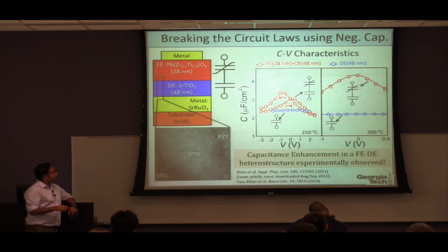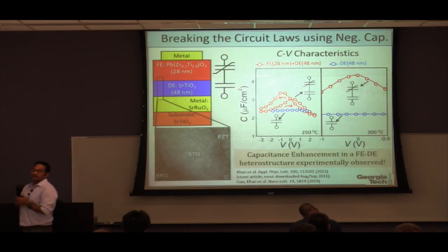So I'll spend some time explaining the result. This blue curve is the capacitance of a 48 nanometer dielectric. And this red curve is the capacitance of a 48 nanometer dielectric plus a 28 nanometer ferroelectric. And what we see is that this 28 plus 48 nanometer heterostructure, total 76 nanometer thick, actually has a capacitance larger than the 48 nanometer film, which essentially means that this 28 nanometer film is working as a negative capacitance. What you would expect is that a 76 nanometer heterostructure will have a smaller capacitance than a 48 nanometer structure, but essentially what we are seeing is opposite to that.